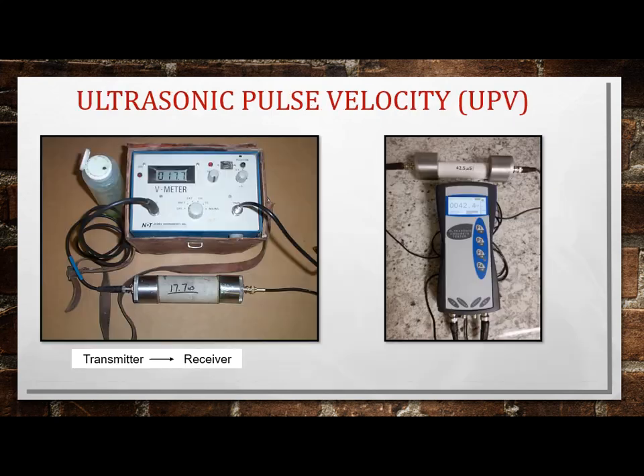But it's a tap test. So this is another tool, ultrasonic pulse velocity. This is a tool in the specifications. You've read it, where if your concrete cylinders don't make the strength, it says to test with non-destructive methods, and it says either use core drilling, rebound hammer, or sonoscope. So this is the sonoscope they're talking about.